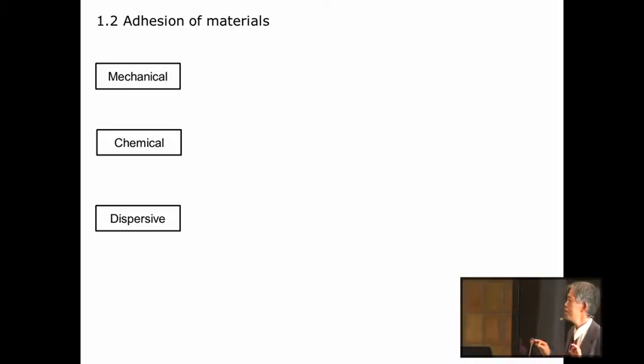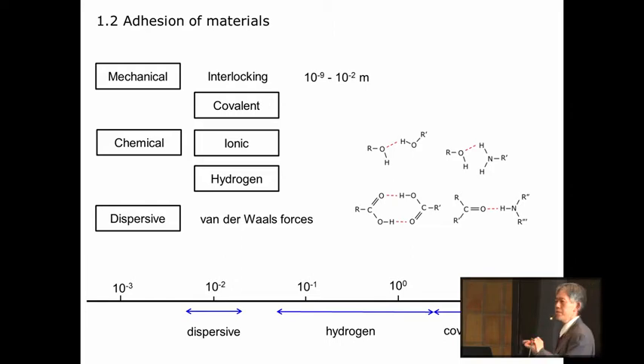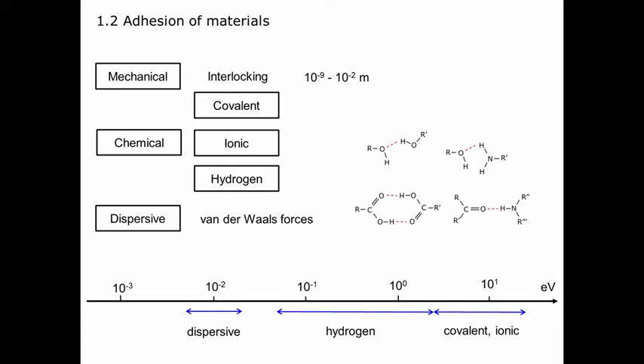You may think it's easy, but it's a very, very complicated phenomenon. There are three important effects which can control good adhesion: mechanical bonding, chemical bonding, and also dispersive interaction. You know that if you roughen the surface, you can increase the surface area so that you can increase mechanical interlocking. That's well known. And it's also nice to have some chemical interaction like covalent bond or ionic bond. But in reality, in most cases, especially for the wind industry, hydrogen bond usually plays the dominant effect for good adhesion, because it's not easy to have covalent bond or ionic bond. The range of the force is a bit diverse, and hydrogen bond is a bit weak, but nevertheless, it's very, very important.